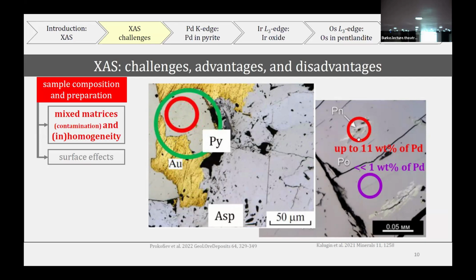And here is an example. This is a palladium-bearing pentlandite. It's extremely enriched in palladium, while the pyrrhotite coinciding with it is almost empty from the chemical point of view. It's almost empty in palladium, even if it's a few hundred ppm. So if you want to record the XAS spectrum in this crystal, if we are touching the pyrrhotite matrix, it doesn't matter. It almost doesn't exist for us. But if we are doing it the other way around, you have to be extremely careful, because one little crystal of pentlandite in this spectrum, and we won't be able to discriminate. Well, we will be able, but it will be much harder.